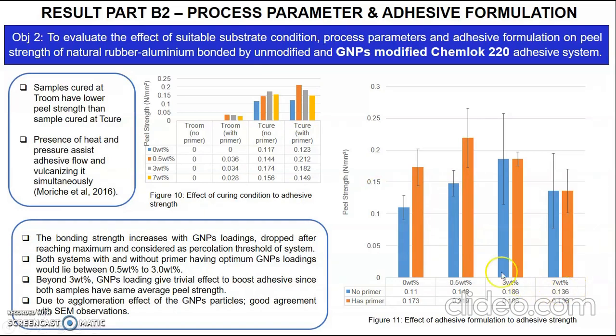You can see that with higher GNP, the peel strength increases. The peel strength increases at higher GNP and drops at a certain weight percent after achieving the maximum value. Beyond 3 weight percent GNP, it gives a trivial effect in boosting adhesion, since both samples have the same average peel strength value.